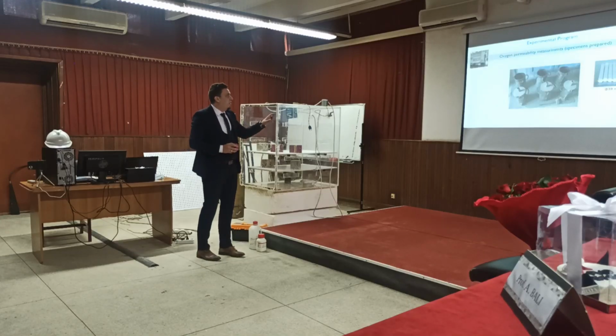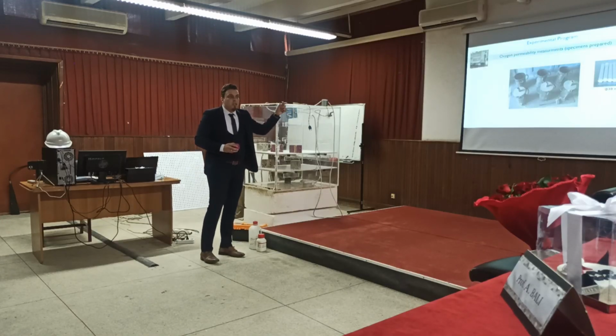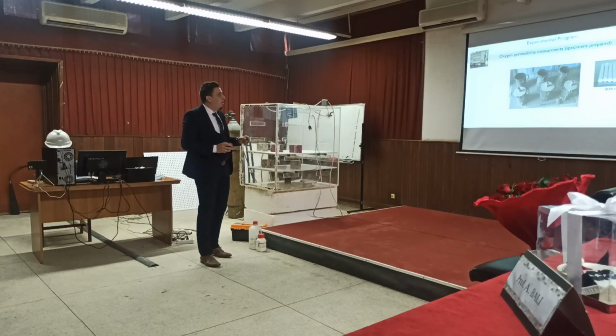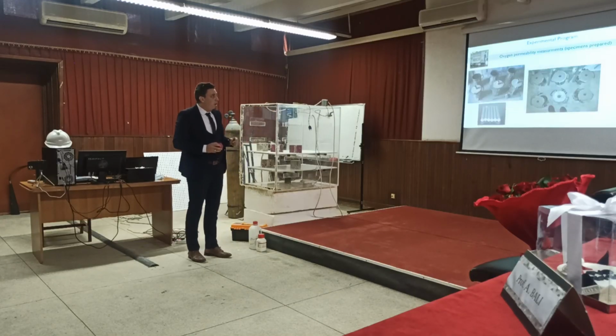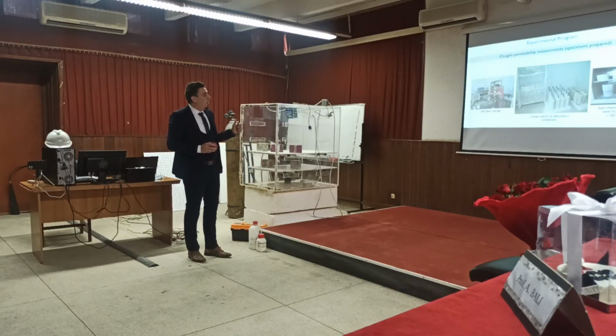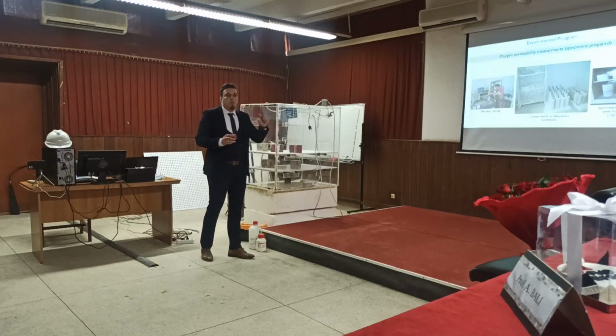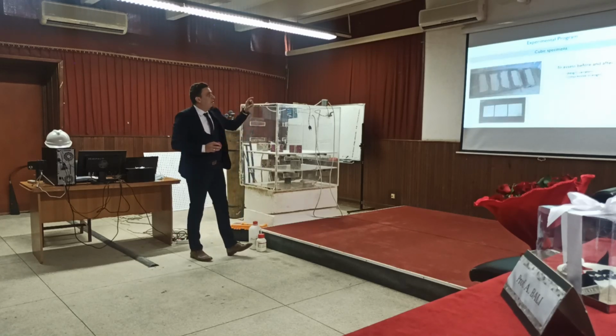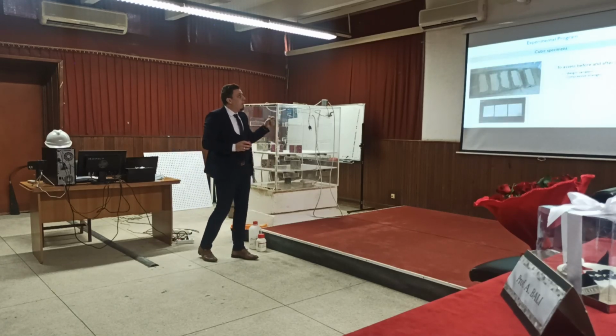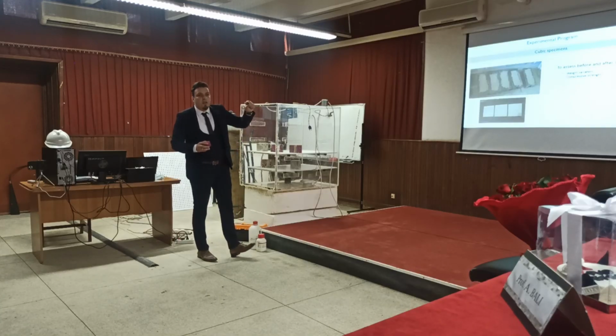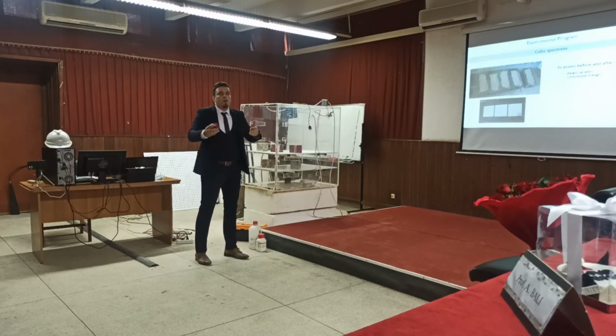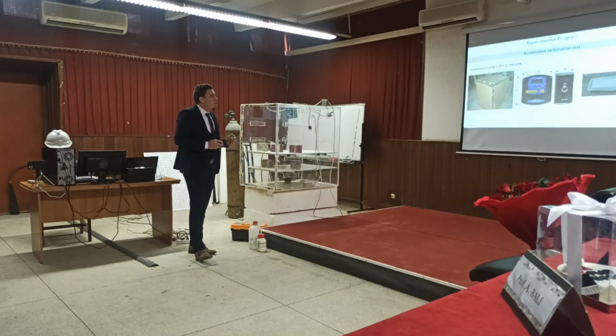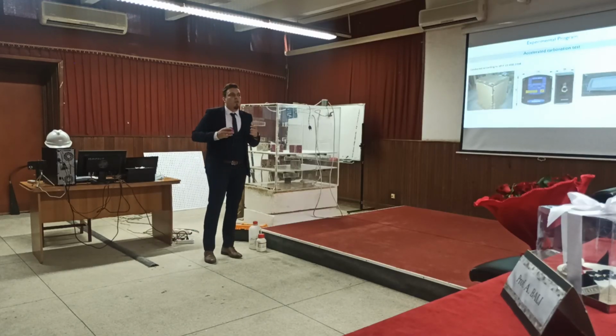This method needs specific specimens with holes, as you see here. The cast specimens are given here, and after 24 hours, we demold them, we cure them, and we saw them in order to get the required thickness, which is 10 centimeters. Besides these specimens, we prepared cubic specimens in order to assess the weight variation and the compressive strength before and after carbonation.